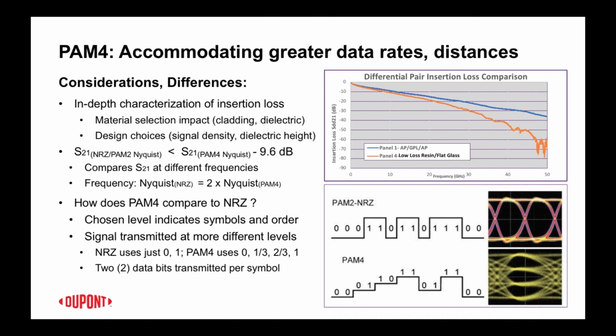In order to take advantage of PAM4, we think there needs to be a pretty in-depth characterization of insertion loss across frequency for the material that you're working with. So one of the first things that's necessary for PAM4 to work relative to NRZ is to get that same amount of data across the differential pairs. PAM4 is able to do it at half the frequency, but we need to understand that half the frequency is going to give enough signal strength to permit splitting that voltage into 4 different levels rather than just 2.